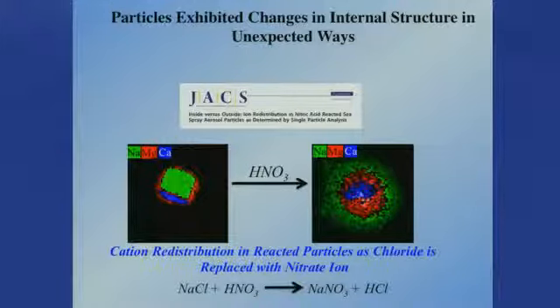Okay, just one more slide, and then I'll wrap up. Kim mentioned this also in her talk. We can use microscopy. This is EDX elemental mapping. We see that particles have a ring of magnesium on the outside, maybe associated with organics. Here we might have just a few organics, and we react with nitric acid. And if you look at the color coding, we see that after reaction, we have a change in the cation distribution within the particle. So we're trying to understand this better.